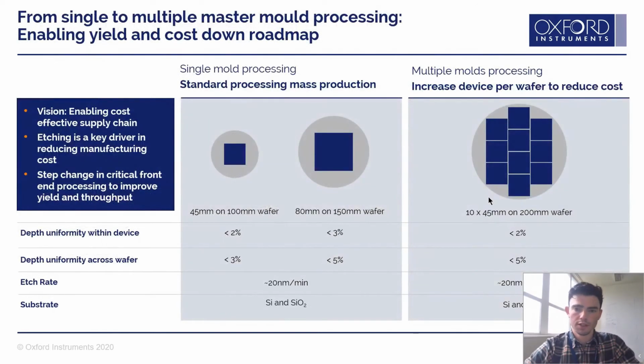The other advantage of this technique is moving from small single molds on one 100mm wafer up to a larger wafer. The uniformity of the etch within devices and across the wafer is good enough to produce 10 of these on the 200mm wafer. Since we're adding in another fabrication step, this increase in efficiency is a great way to reduce cost and really make this a viable technique.